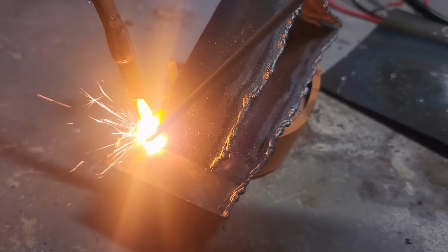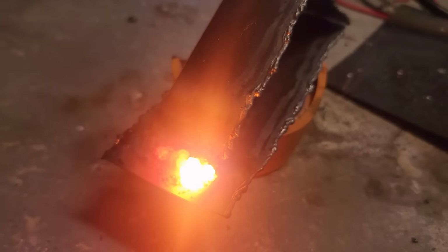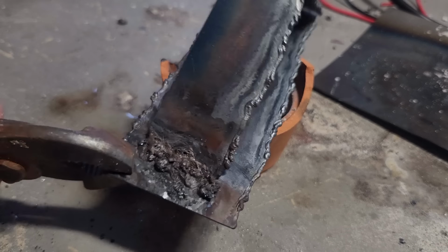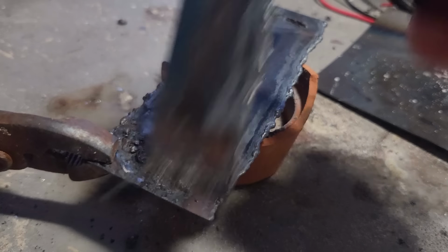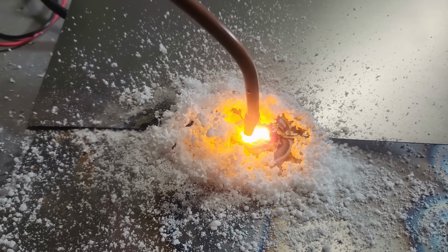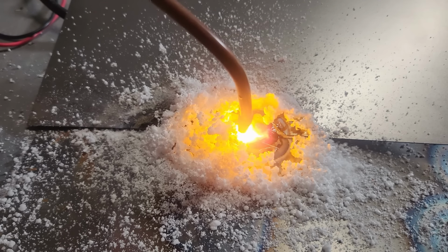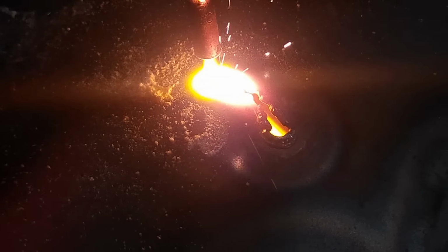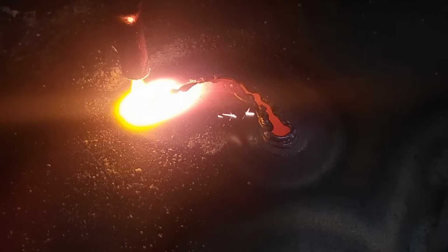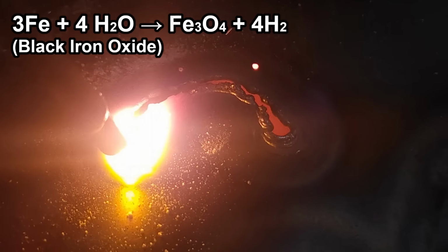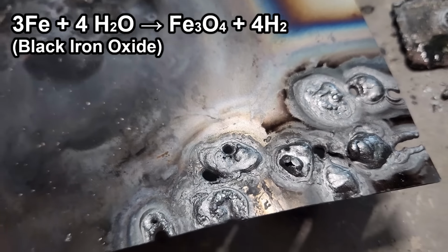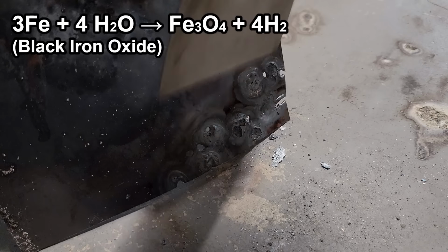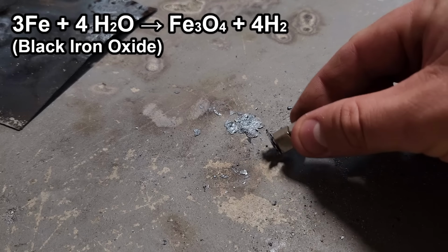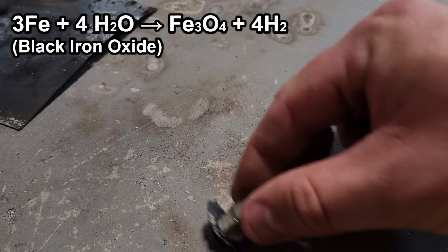Welding is a different story though. I could clearly see a molten pool when I was trying to weld the joint, but the weld is just slag and immediately breaks apart. Even with tons of flux, this still happened, and I think it's just because the flame is essentially just superheated steam, so the water is oxidizing the steel. I think it's the reaction here that's happening, and the slag is magnetite because the oxides are black and still attracted to a magnet. Red iron oxide wouldn't be attracted to a magnet.